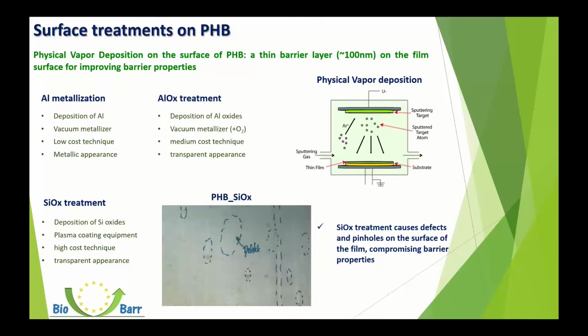With aluminum metallization, we define the deposition of an aluminum thin barrier layer by a vacuum metallizer, and it is a very widely used technique in flexible packaging, as it is a low-cost technique to improve barrier properties. However, this technique causes a metallic appearance of the films, so it compromises the transparency of the polymer.